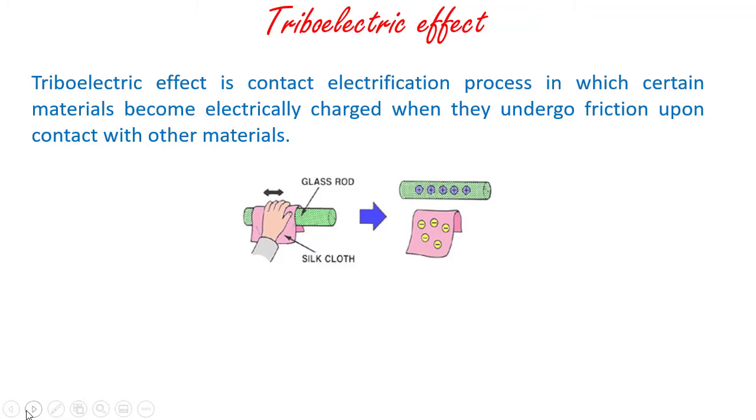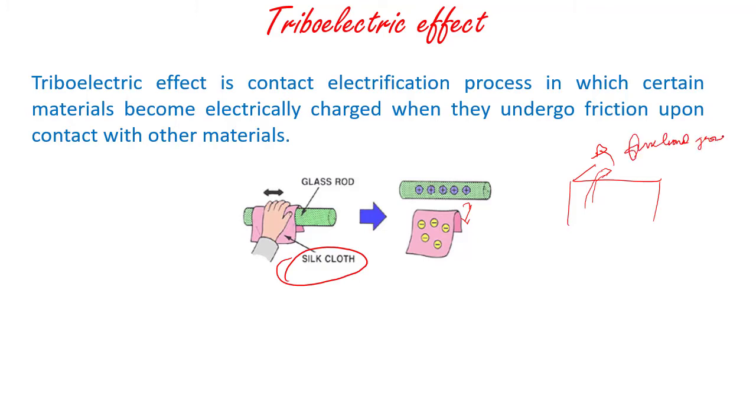But what you are seeing there is the triboelectric effect. That is, for example, it's known that if you take a silk cloth and rub it against a glass rod, there is some exchange of charge. Here in the example, if this is the desk and you have a piece of tape here, when you peel this tape off, there are organic functional groups within the polymers that make up the tape. Those get ionized, those get charged because some bonds break, and because of that, you see that they're differently charged